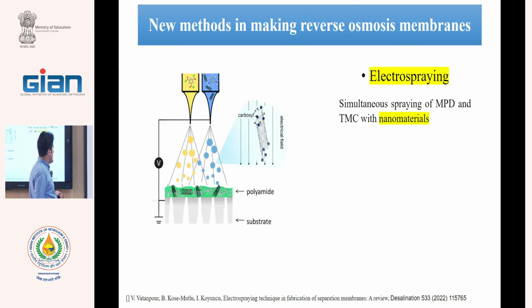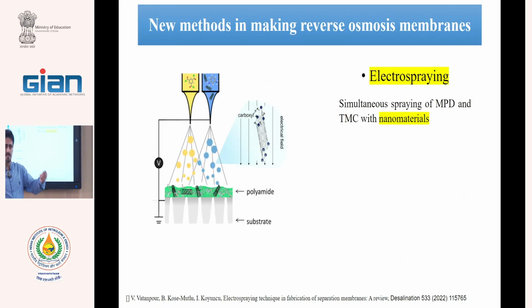Show the electro-spraying. In all of these methods, as I will discuss in the next lecture about the fabrication of nanocomposite membranes, we can use the nanomaterials in the MPD solution or in the TMC solution. If the nanoparticle is well dispersed in the organic phase, we add it to the hexane solution. If well dispersed in water, we add it to the water solution. And with spraying, we have a mix of polyamide and nanomaterials, here using the carbon nanotube.